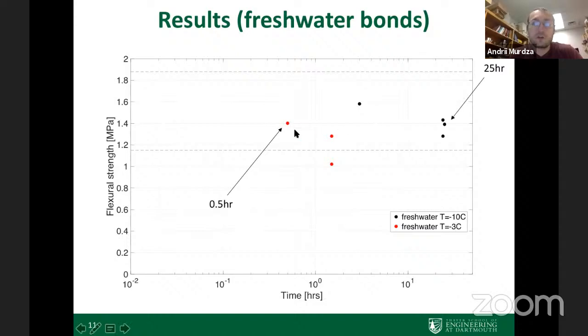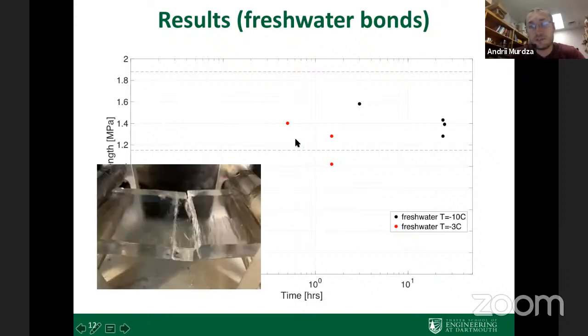And so the conclusion from here we can make is that even half an hour is enough for the freeze bond to reach the full strength, sort of. So the freezing occurs in less than half an hour. And one important thing to know is that in all of these cases,